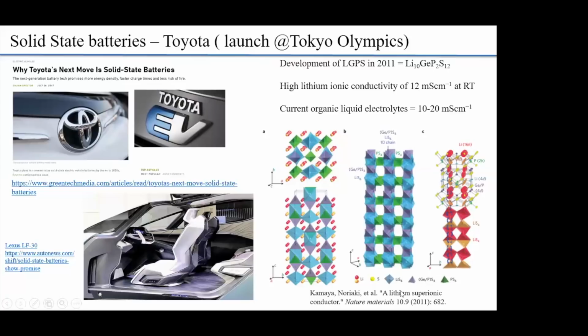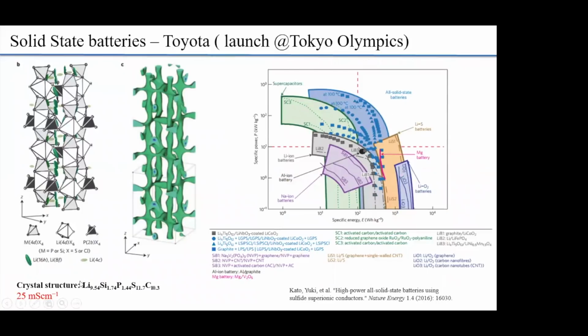They published this paper called a lithium superionic conductor, and they proceeded to develop more on it. In 2016, they improved upon it. So they had lithium, silicon, phosphorus, sulfide with some chlorine on it. And that had a remarkable ionic conductivity of 25 millisiemens per centimeter. That is remarkable for a solid electrolyte. You can see this is the skeletal structure, and within the skeleton, you have lithium. The green structure shows where lithium can go. You can see long pathways, which provide a wonderful connected pathway for lithium to go from one side to the other. That's why they call it a superionic conductor for lithium.